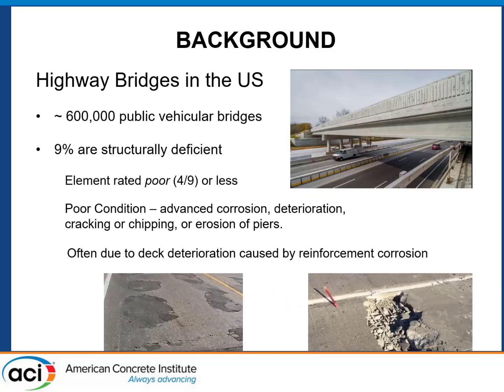So there's about 600,000 public vehicular bridges in the U.S., and of those, about 9% are rated structurally deficient. That means one or more elements had a rating of poor, 4 out of 9 or less. Poor condition could be due to advanced corrosion, deterioration, cracking, and some other effects as well. But these are often due to deck deterioration caused by reinforcing corrosion. And here are a couple of pictures of actual bridge decks.